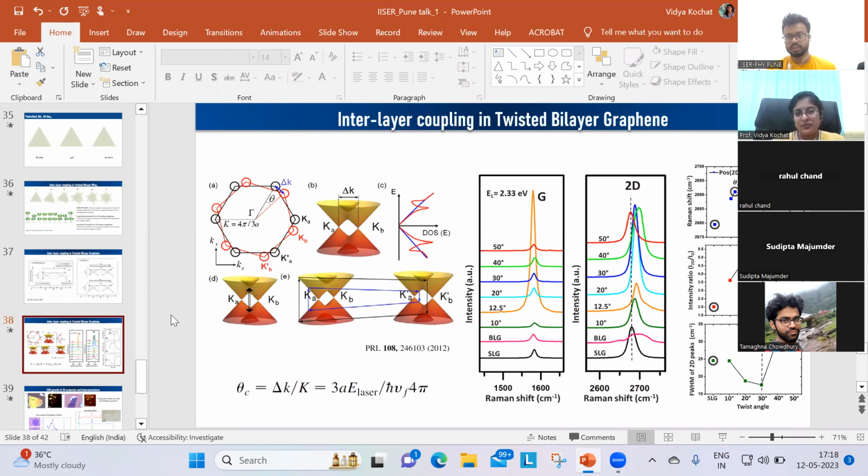But you have to optimize the transfer technique, because maybe if you use a different polymer, like say PC, which can go to higher temperature, then you might be able to pick up at higher temperature. So it is always an interplay. You need to study the adhesion energies as a function of temperature and see what would be the ideal temperature range for picking up each sample.